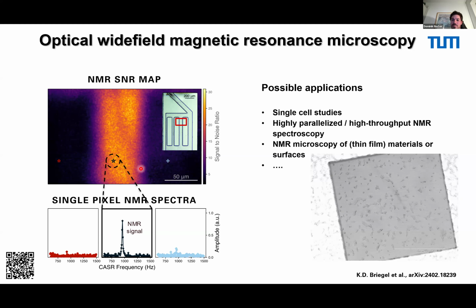Other groups have shown much better numbers, but here we really tried to get the NMR signal and totally neglected anything on the sensitivity. That's really what we're doing now. I'm pretty sure we can improve this by orders of magnitude. But again, for biology it will still be hard to go down to very, very low concentrations. So don't be shocked if you look at the paper and see, oh, this 10 hours of averaging. We did not focus on the sensitivity for this publication.